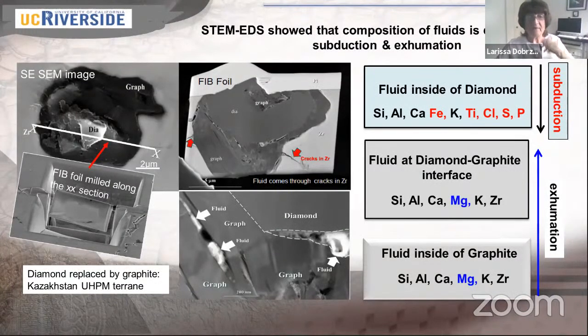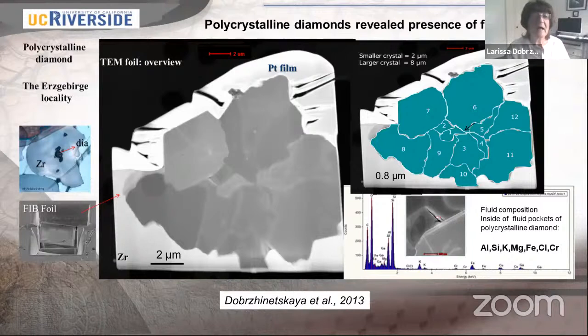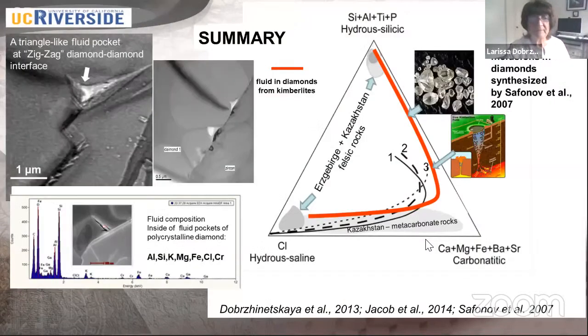So then we study another material. We study diamond inclusion in graphite, and we also found a lot of fluid here, and we were able to discriminate this fluid inside of diamond. We also found chlorine, sulfur, silica, aluminum, calcium, and again, focus ion beam helped us. Then we study polycrystalline diamonds, which we discovered again within zircon. This is a foil that was prepared. You see here 12 crystals inside of this polycrystalline setup. We also found fluid pockets here and measured their composition.